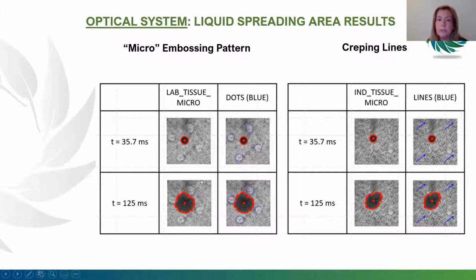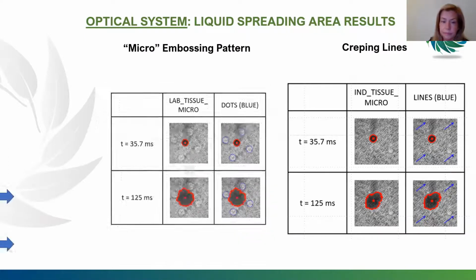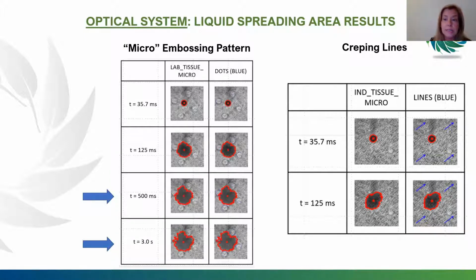In the image on the left, here, the embossing micro pattern dots are signalized in blue, and it's visible that the flow, the spreading, is changed by the influence of these topographic effects. When the time progresses, we can see here that for the time of 3 seconds, there are spreading irregularities provoked by the dots, and the liquid goes around and into the valley effect, the concavity effect made by these dots.